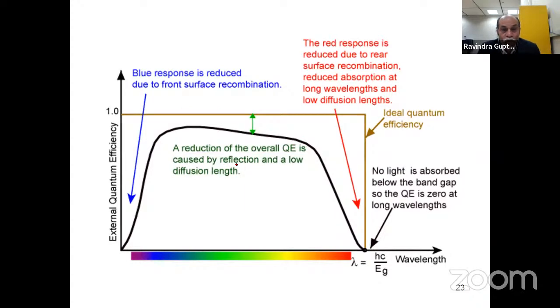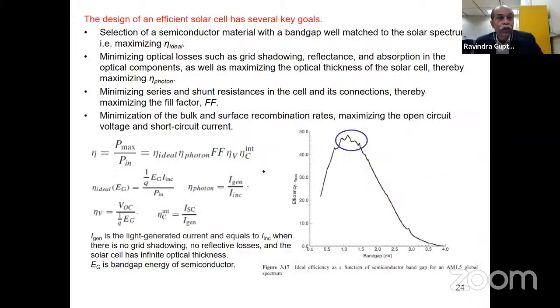So we have to reduce the reflection. The loss should be very, very low, and the diffusion length should be as high as possible. The red response is due to the rear backside surface recombination, as well as the long wavelength. If we are going towards the infrared, naturally energy is less, so naturally the photon conversion to electricity will be less. And if it is less than the band gap of the semiconductor, naturally no conversion.